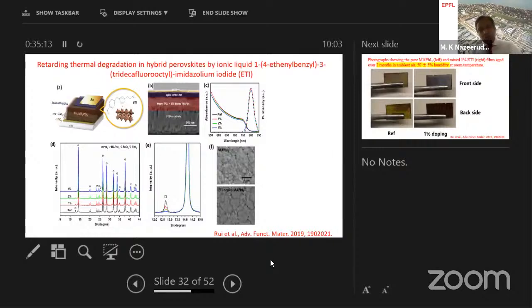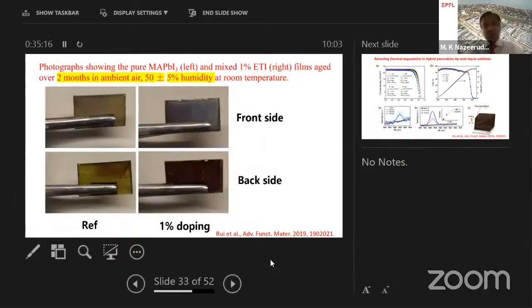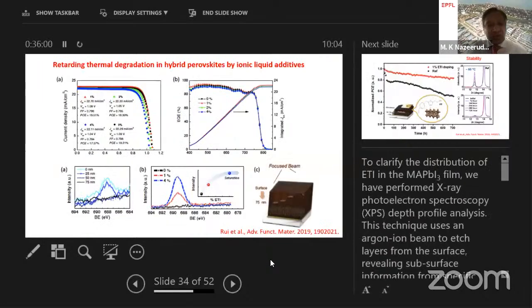The next slide shows the beauty of having 1% of this ionic liquid in the perovskite composition. On the right panel, what we are seeing is the front side and then the back side of the 1% ionic liquid doped perovskite solar cells. On the left side, as a reference sample, over a 2 month period, when exposed to ambient air with 50% humidity, the perovskite color is disappearing. The presence of 1% ionic liquid clearly shows the enhanced stability of this material. Now, the question for students is, what is this ionic liquid doing? In the next slide, I put in information so that they understand what is happening here.